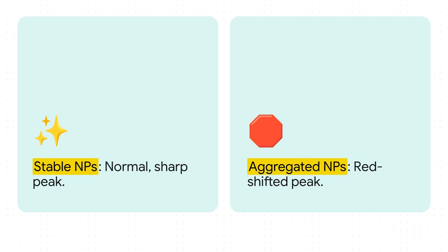In a perfect scenario, your nanoparticles stay perfectly separated and stable in solution, which gives you that sharp, normal SPR peak. But if things start failing and they clump together, a total nightmare called aggregation, their individual electron clouds start messing with each other. This drastically alters their optical signature. The peak widens out, flattens down in a process we call damping, and it exhibits a massive red shift. Visually, your liquid might suddenly shift from red to blue or purple. This is an instant red flag for a researcher that their particles are clumping up and losing stability.